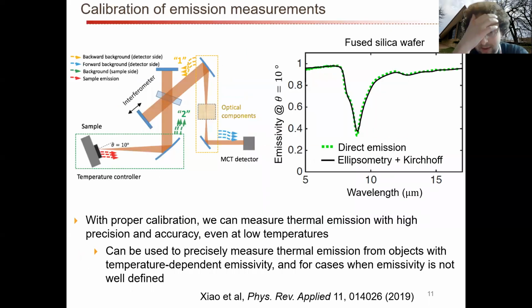We spent a lot of time trying to calibrate our experimental measurements, taking care of things like thermal emission that's kind of background emission moving in the forward direction, background emission moving in the backward direction, which does some very funky things to the resulting spectrum if you naively try to extract it. It's really not that easy to do, but when all is said and done, we can actually get very, very good thermal emission measurements.